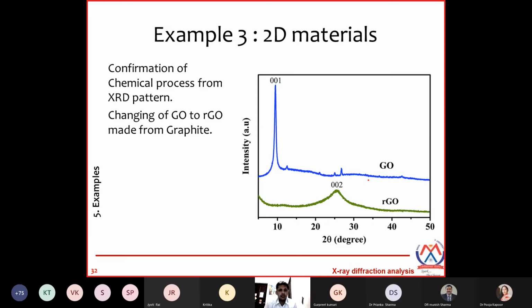There are lots of analyses like this in 2D space, for MoS2 and other materials also. So we use this XRD analysis so that we can understand the kind of changes taking place in the material. So whenever I write about this, I should convey to the editor that I am claiming the synthesis of RGO because the interplanar distance has come back to the position where it should be. I should not directly write it like, because the location of the peak is over here, that's why reduced graphene oxide has been synthesized.